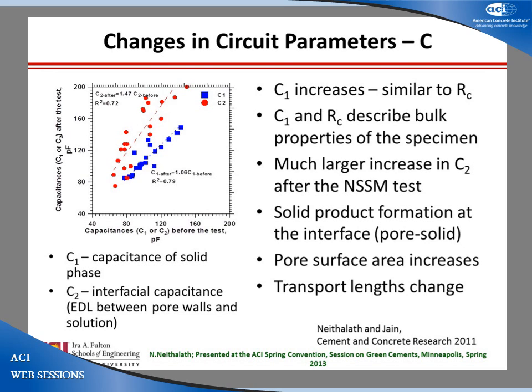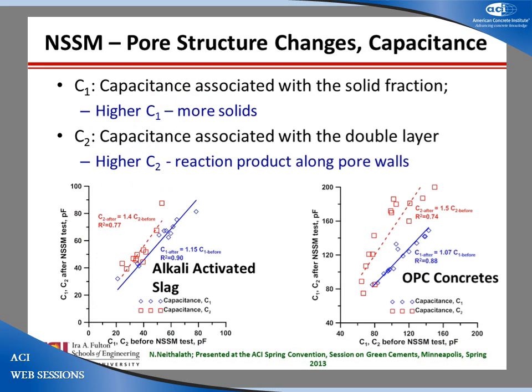This is for conventional concretes after you do a non-steady state migration test. So if you look at that, you can see that alkali activated slag and OPC concretes follow a very similar trend with non-steady state migration. So the takeaway from here is if you're doing an RCP test with alkali activated mixes, be a little careful because they don't really tell you, because it is dependent on the pore solution conductivity, the microstructure, the electrical properties, all of that. We like to use RCPT because it's pretty quick, you get a lot of good results, but for alkali activated concretes, RCPT will make them look better than what they are.